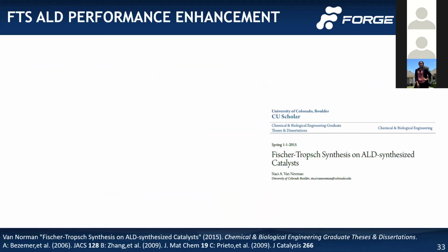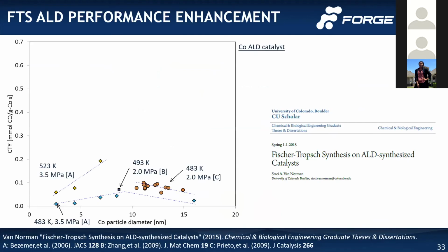This is from the University of Colorado at Boulder, where I did Fischer-Tropsch synthesis with an ALD catalyst. So it was a cobalt deposition, a metallic deposition of cobalt.